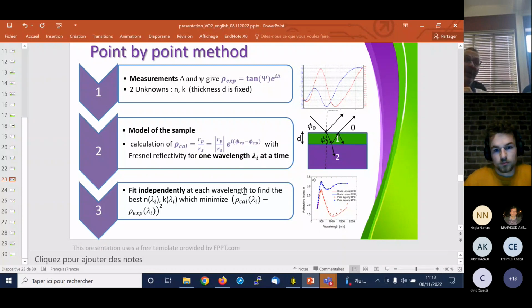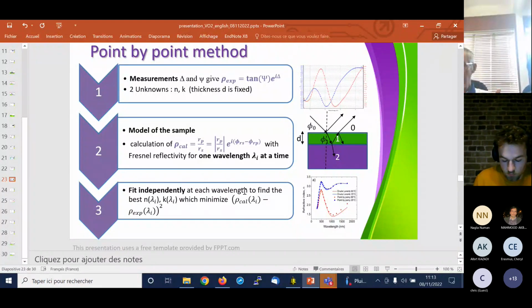So this is why, when we looked at what he was saying, we said, okay, maybe we should do what he's saying. Should be better. And so we did that. It took us a little bit of time to understand the point-by-point method, but nonetheless, we did it. And in the end, you can see that it was extremely relevant, because for pure VO2, there is not much of a difference, but if you go into doped materials, you can see that the standard technique does not give you the right answer. So it's much better to use the point-by-point method.